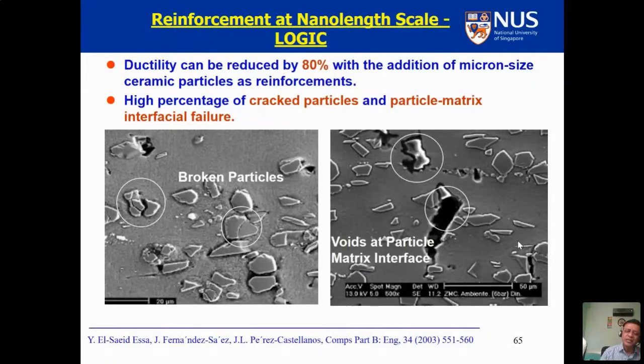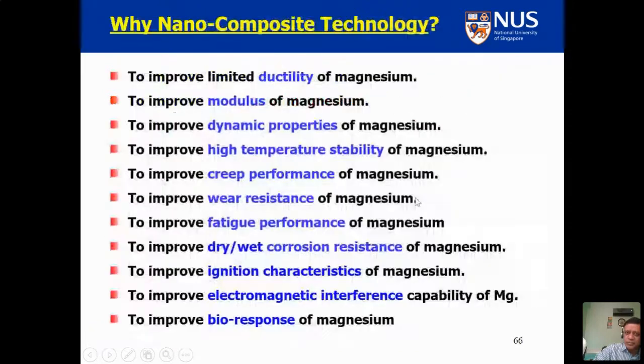Now, what is the problem with the micron length scale particle is that when you subject the material to tensile loading or any kind of loading, the particle can break, as you see on the left hand side image, or they can debond from the matrix, leading to the formation of cracks. If these two particle based damage mechanisms are initiated, you compromise on the ductility by 80%, you compromise on the fracture toughness, and you compromise on the ultimate tensile strength. And that is where, when you put the nano reinforcement, you may get all these advantages.